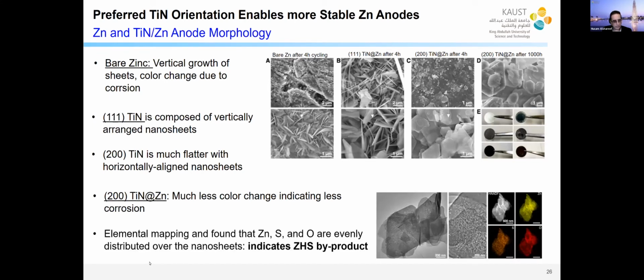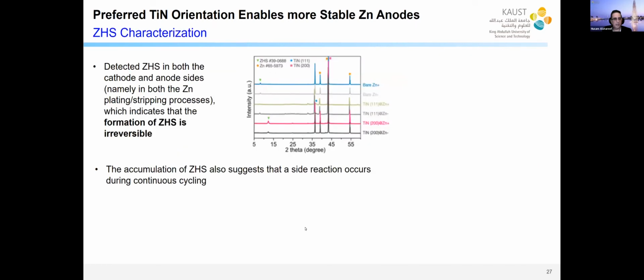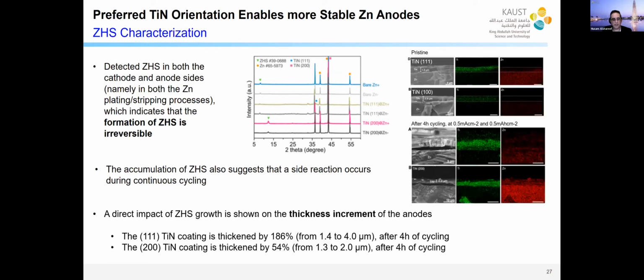And so we looked at the elemental mapping of the samples, and we found out, especially for the bare zinc and the 111 titanium nitride, that we have this byproduct, ZHS, forming on the surface. Again, this is the sulfur, this is the zinc. That's a common byproduct in this zinc battery. So we have to always find a way to get rid of it. So we analyzed this for these different samples, the bare zinc, the titanium nitride 111, and the 200. There's in fact a formation for all of them, but the amount actually is different. So for example, if you look at the thickness, these pristine samples on the top.